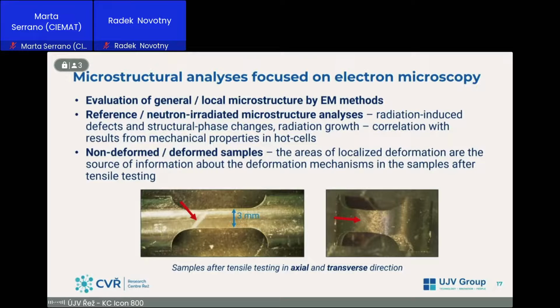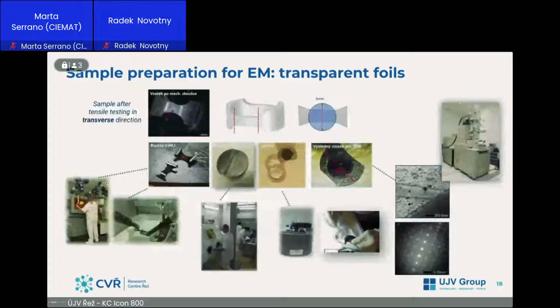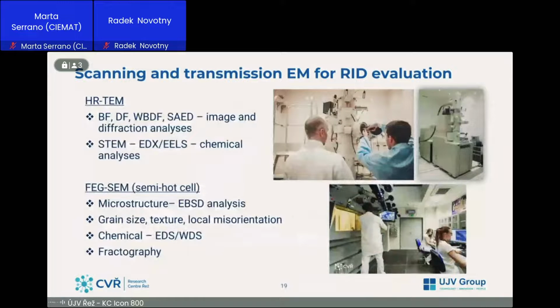Here's the example of tensile testing in axial and transverse direction from the cladding tube. So here's the workflow, how to prepare the specimen from the transverse sample, from the transverse direction after mechanical testing. So we choose the place and do the cutting, grinding and polishing to obtain the final thin foil to observe the radiation-induced damage in transmission electron microscope. So these irradiated materials are prepared in hot cells and glove boxes.